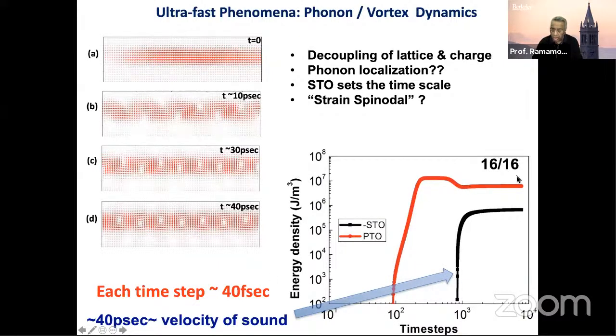Okay, that's the total energy of the system as a function of time in time steps. This is about 40 picoseconds, which is the velocity of sound in the system. As you see this, the lead titanate layer gets to its maximum energy density within about a few picoseconds, which are all the dipolar interactions. But the strontium titanate actually takes a long time. And we think that's because there's an acoustic phonon that's being launched, which is important in the formation of this vortex. This work is still being resolved because we need to understand it fully. But it's telling you that with the combination of these ultra-fast X-ray probes and theory, you can start to understand the formation of these kinds of vortices.